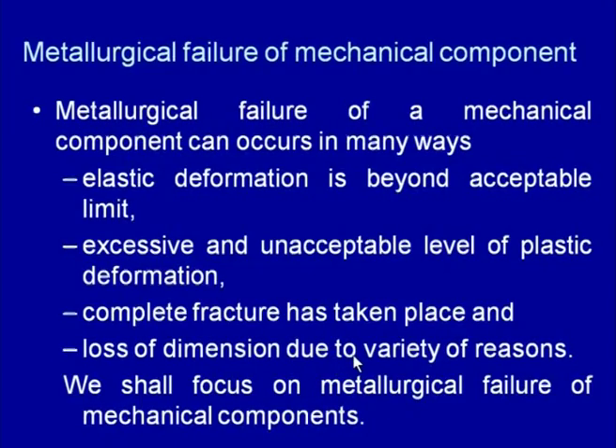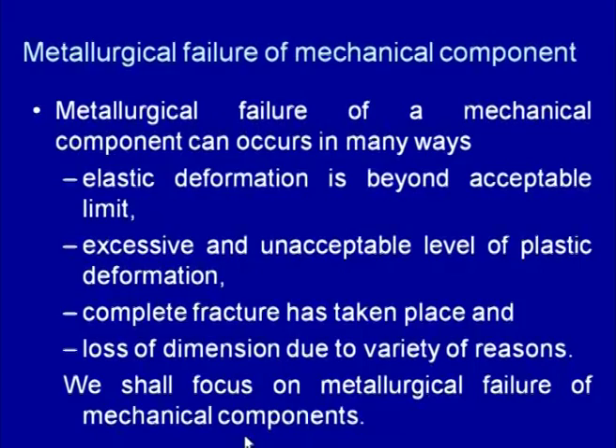There may be one more situation where, during the service, the component loses its dimensions due to a variety of reasons, and these reasons are mostly related to wear, like the component being subjected to adhesive wear, abrasive wear, solid particle erosion, cavitation, corrosion, or a variety of forms of wear which are commonly encountered by mechanical components during service. So, all these can contribute to changing the dimensions of the component during service, and the loss of dimensions beyond the acceptable limits can lead to malfunctioning of the component. So, then also we can say that the component has failed. In this particular presentation, mainly we will be focusing on the metallurgical failure of mechanical components.